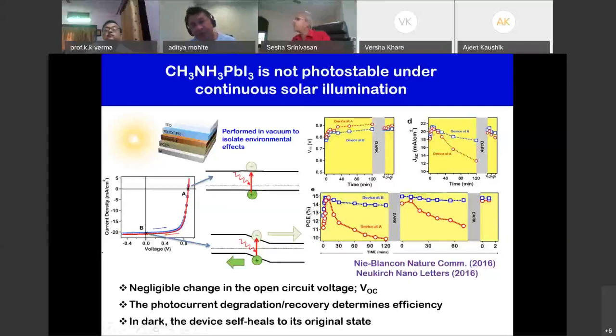But your short circuit current does something very interesting. It increases, but then over time it kept decreasing like this. Okay. And so if you turn your lights off again, you found that your short circuit current sort of self-healed. It went back to its original value, and then it continued doing the same thing. And so we explain this by the formation of light-induced trap states within the band gap of this material. Nevertheless, I won't go into details of this.